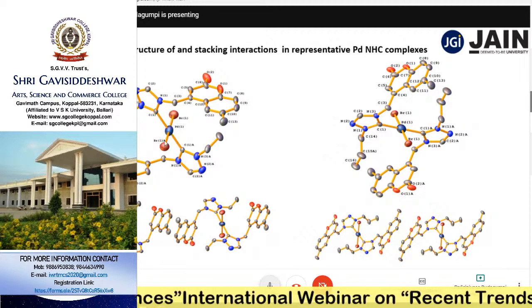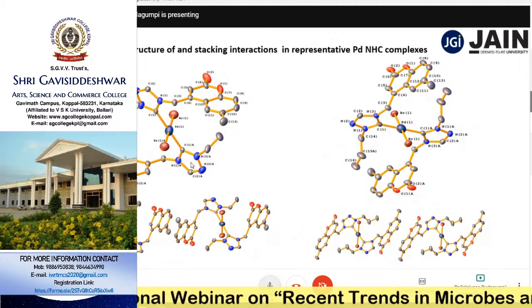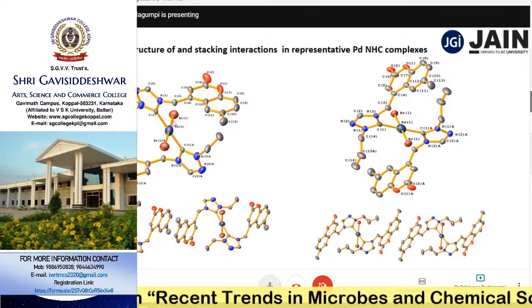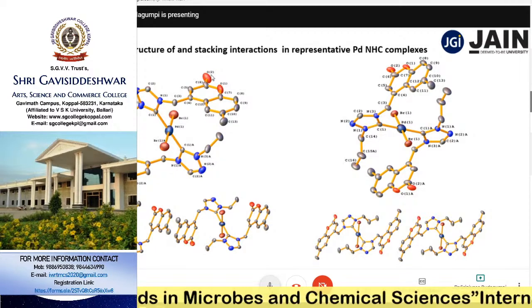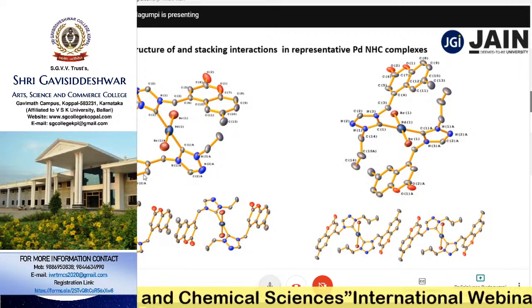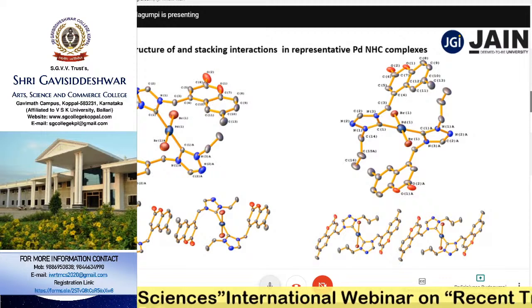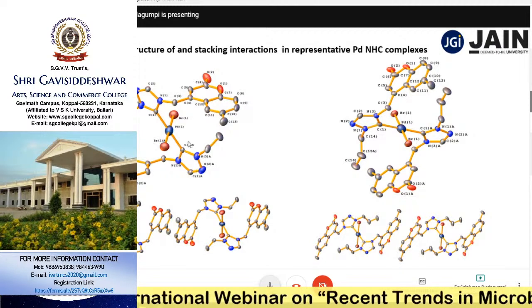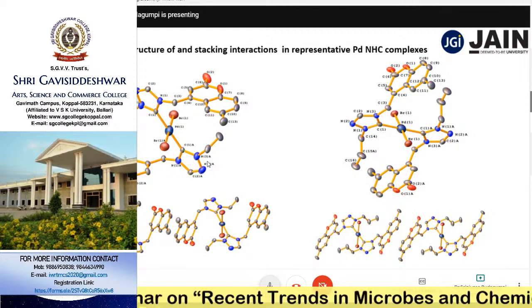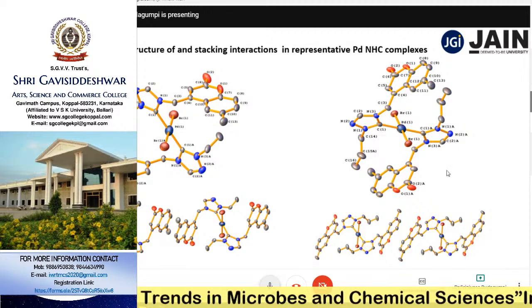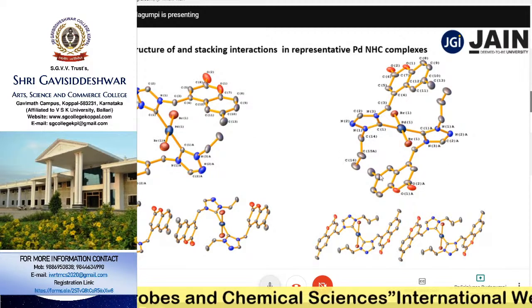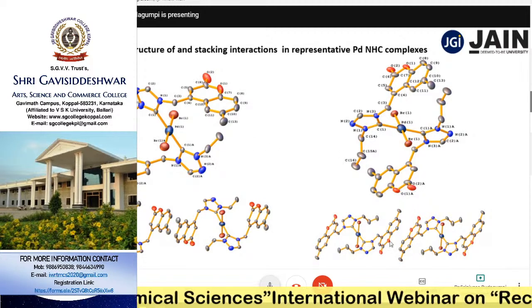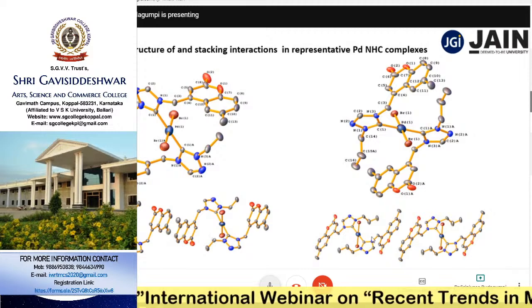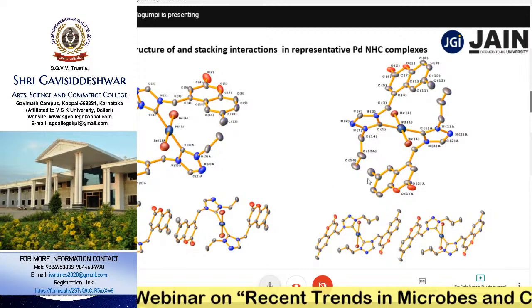So this is trans arrangement because these ligands are trans to each other. Both NHC ligands are trans to each other. Bromido ligands are trans to each other. And the coumarin substituents are on the opposite sides of both the NHCs. This confirms the trans-anti arrangement. And because of the presence of electron density in the coumarin substitutions, stacking interactions are possible. So these are the stacking interactions of the same complexes.